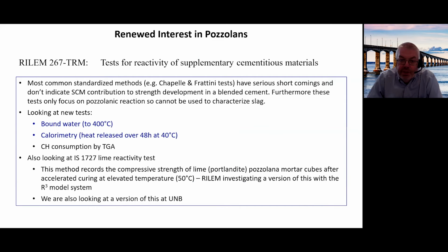In Europe, it's a similar situation because new supplementary cementing materials are appearing to replace things like fly ash. There are concerns about how we would test for the reactivity of these materials, and a number of test methods have been developed by this RILEM committee, two of which have now been adopted by ASTM. We actually now have two new test methods this year that are able to measure the chemical reactivity of SCMs directly rather than measuring it indirectly through things like the strength activity.